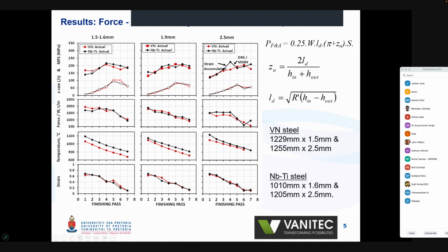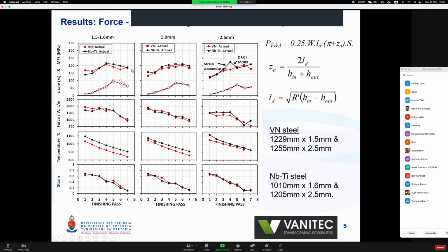comparing vanadium against niobium titanium over here. You will see, if you just scan left to right, that the mean flow stress, the top graphs, are comparable in both grades, and the plots below are the strain rates that were applied during each finishing stage.